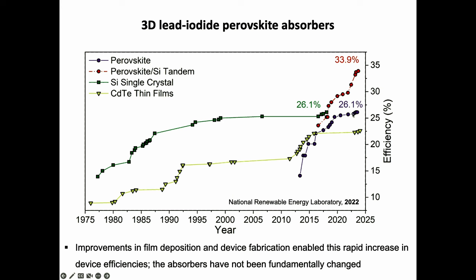And I would argue that the real excitement in this field is in tandems. So these are solar cells that have two absorbers, a low band gap material like silicon to absorb the low energy photons from the sun, and a higher band gap material, in this case, the perovskite, to absorb the higher energy photons from the sun. And there's so much excitement at the fact that this is now exceeding 30%.